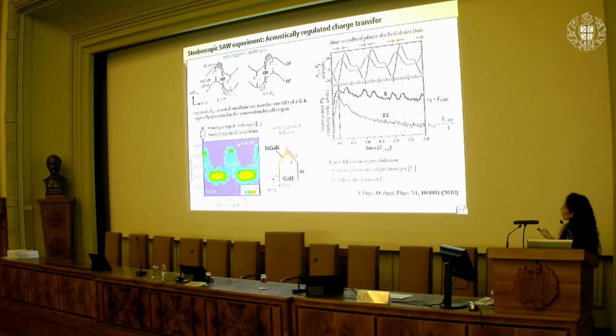So we basically conclude that these intensity oscillations are a result of the periodic field-assisted simultaneous transfer into the quantum dot of the electrons and holes that are optically generated in the surrounding region, so around the quantum dot, in this optically probed nanowire apex.